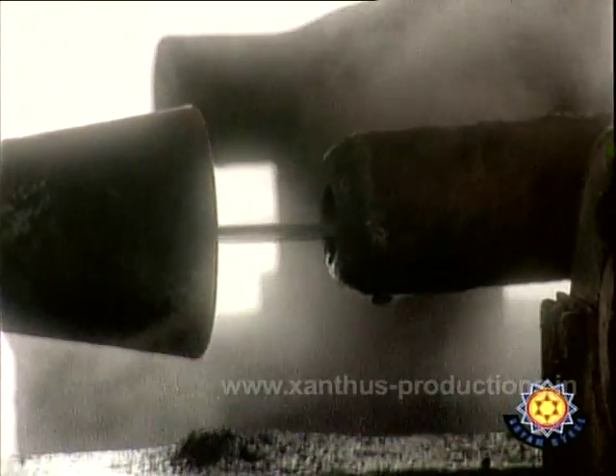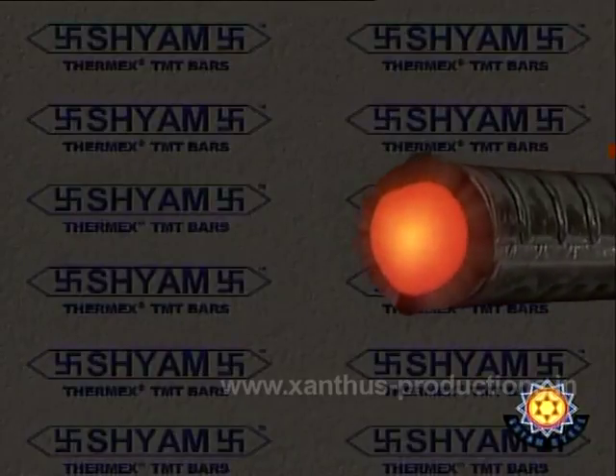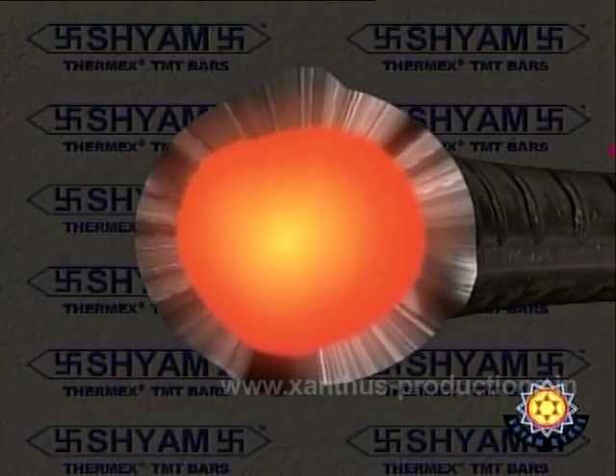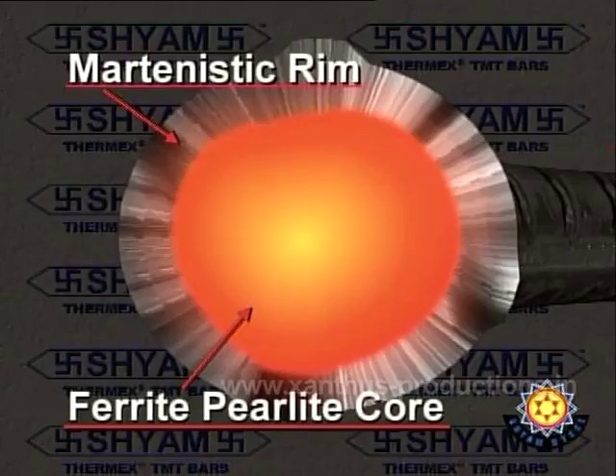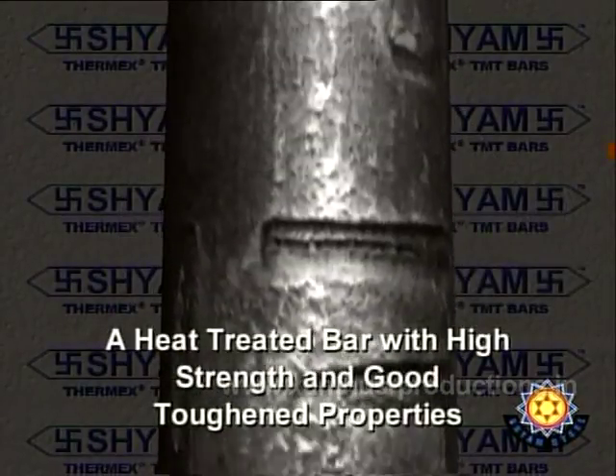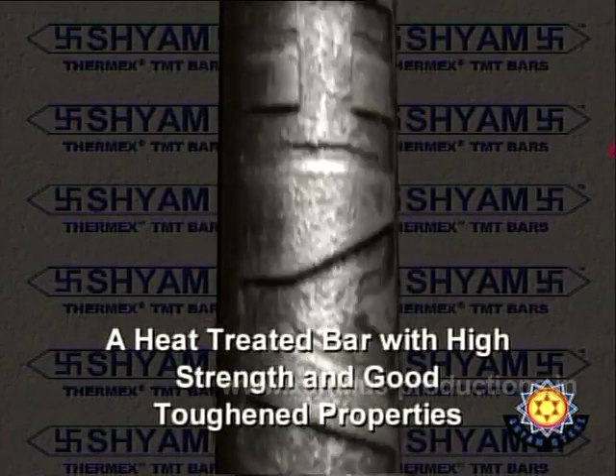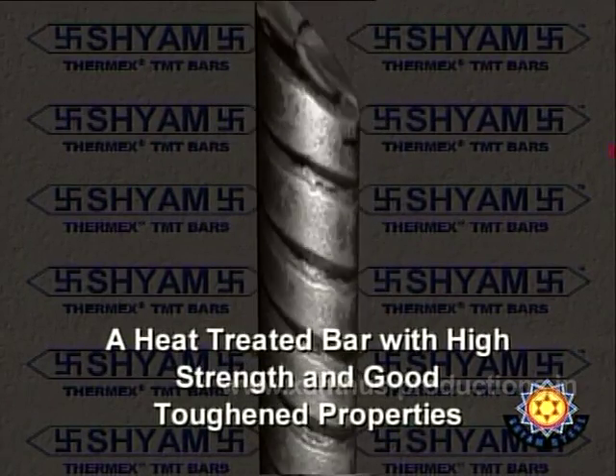As a result, the surface layer of the steel converts to a hardened structure called martensite, whereas the core remains austenitic. The heat existing in the steel bar core causes the surface temperature to increase, resulting in a heat-treated structure with high strength and good toughness properties.